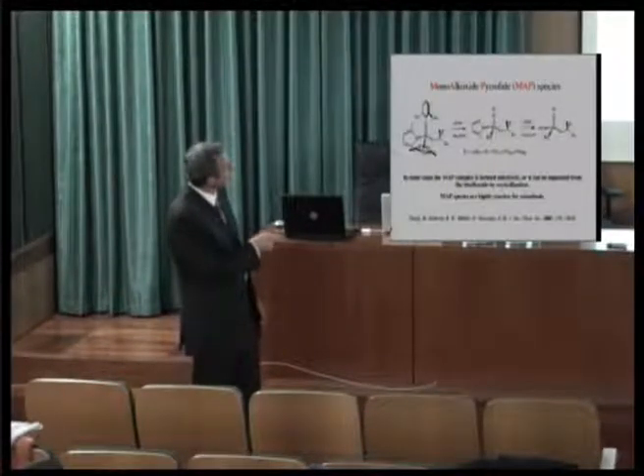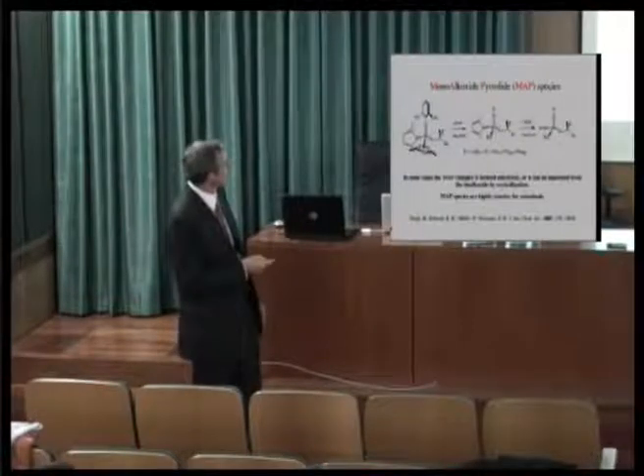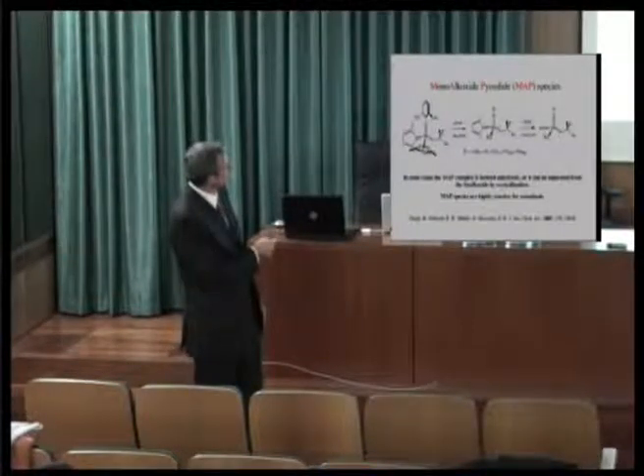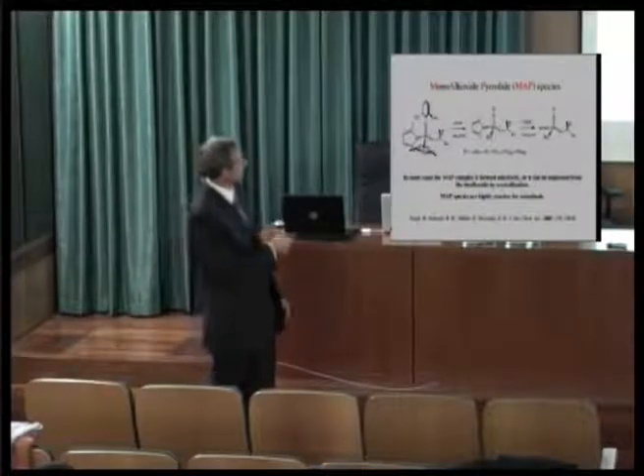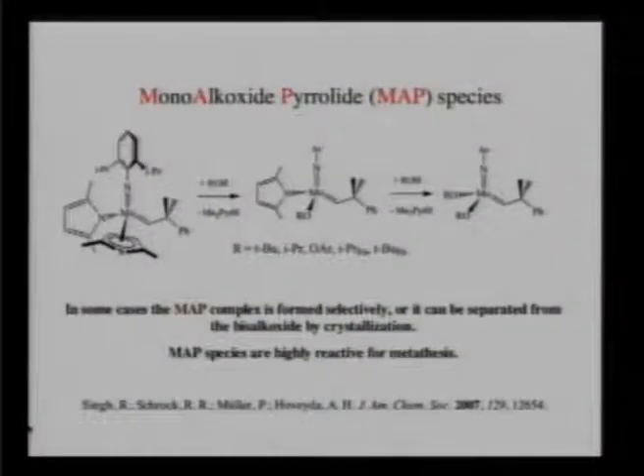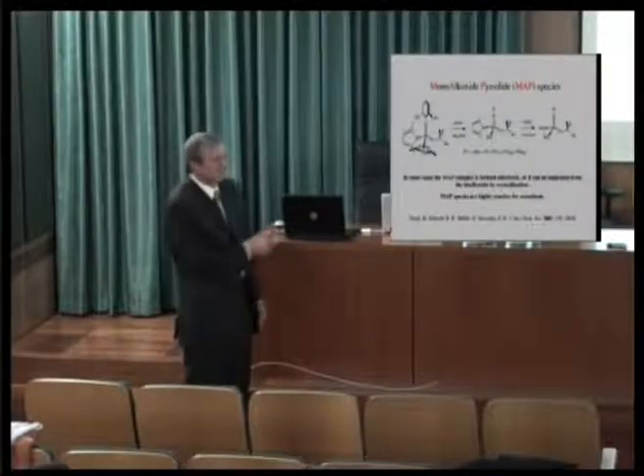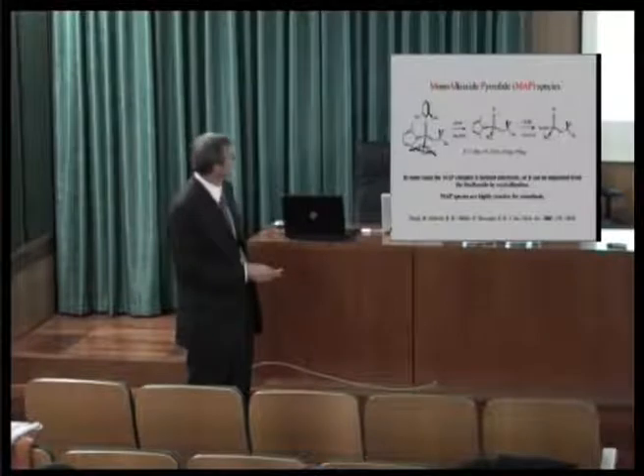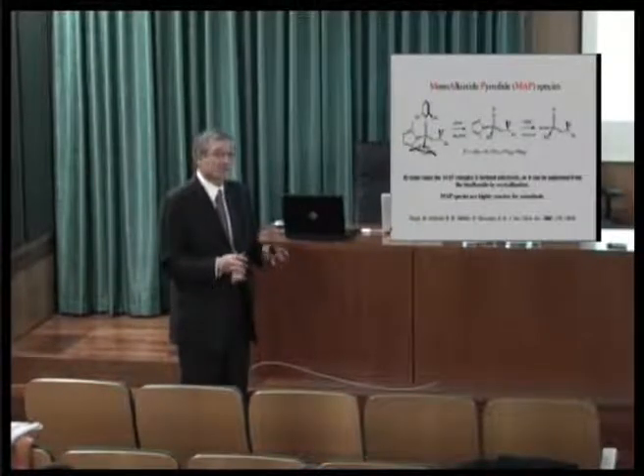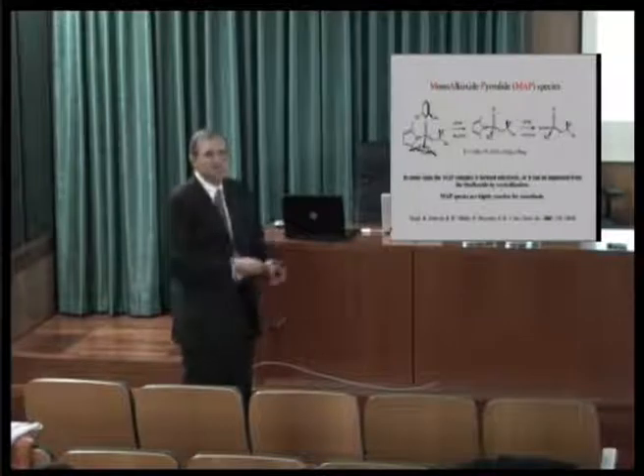An intermediate in that reaction is the subject that I want to talk about tonight, the so-called monoalkoxide pyrrolide species shown here. So that's formed sometimes selectively, and you can crystallize it out. And we expected it not to be very reactive, somewhere between this species, which is not very reactive, and this one, which we know is highly successful for the metathesis reaction. But it turns out that these, for reasons that are not clear, are in general probably 100 times more reactive than these. So we don't know why.